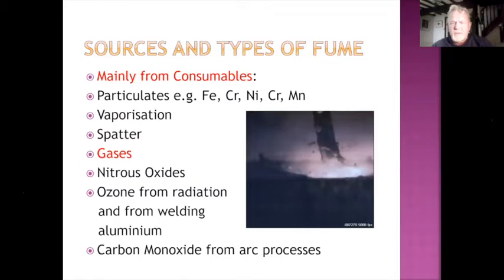When we look at consumables, we're predominantly talking about iron, chromium, nickel, manganese would be in there, could be titanium, there could be niobium, there could be molybdenum. Some of this will vaporize by the very nature of the arc you create and the amount of gap that you give between the end of your electrode and the workpiece. If you're operating at very high currents, higher than you need to, and perhaps using a CO2 gas instead of an argon CO2 gas, you can produce considerable spatter.